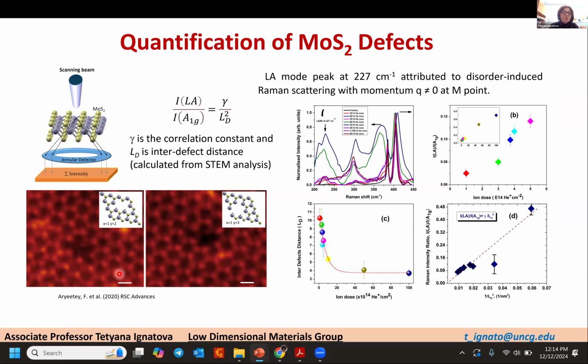You can see here how defects were created. Each time we quantified these defects and identified how many atoms are missing, and we plotted inter-defect distance depending on helium ion dosage. We also brought the same sample to a Raman instrument and took Raman data. Raman data showed significant changes in the two main Raman peaks with increasing helium ion dosage, but we also found the appearance of a longitudinal acoustical mode at 227, which is attributed in literature to defect-induced scattering from the M point.